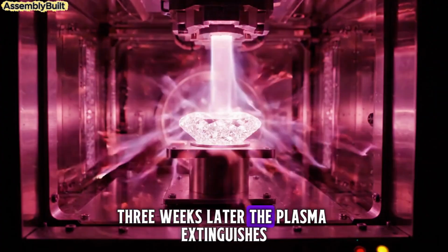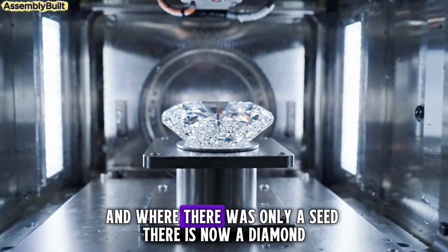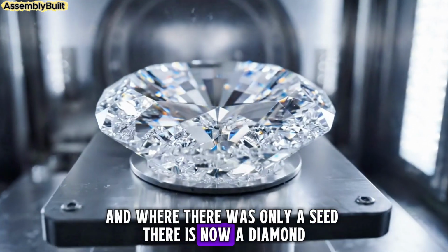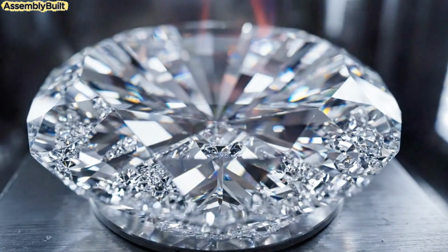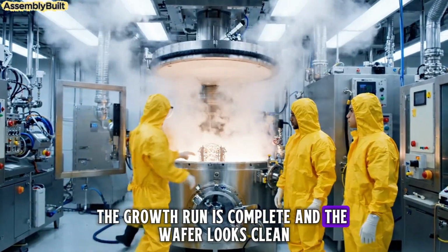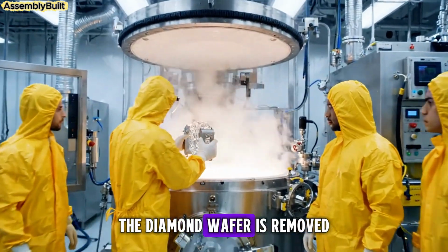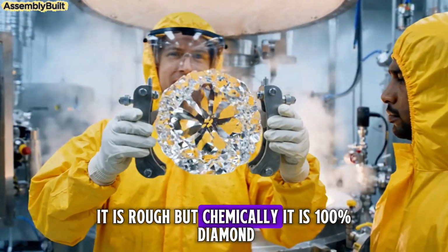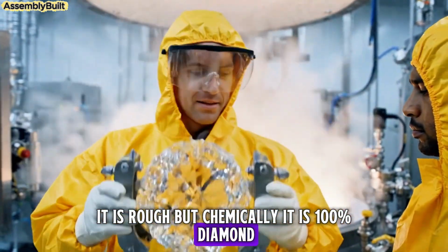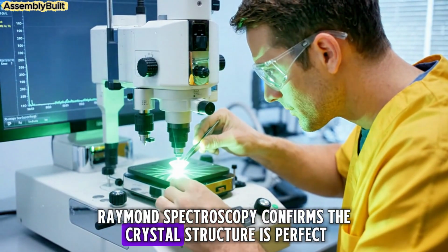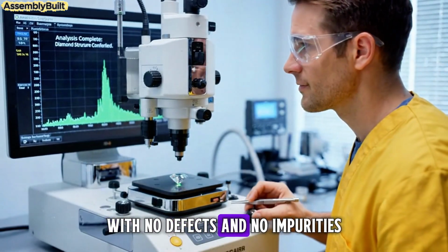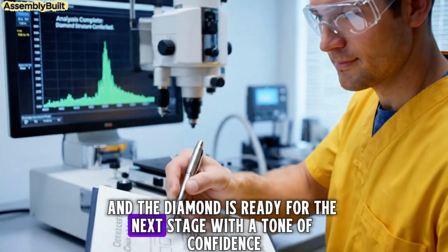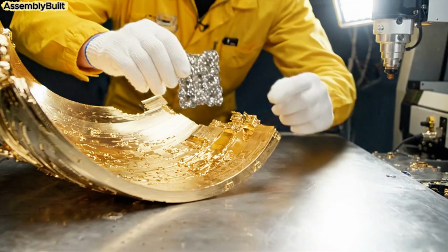Three weeks later, the plasma extinguishes, and where there was only a seed, there is now a diamond. The growth run is complete and the wafer looks clean. The diamond wafer is removed. It is rough, but chemically it is 100% diamond. Raman spectroscopy confirms the crystal structure is perfect with no defects and no impurities, and the diamond is ready for the next stage.